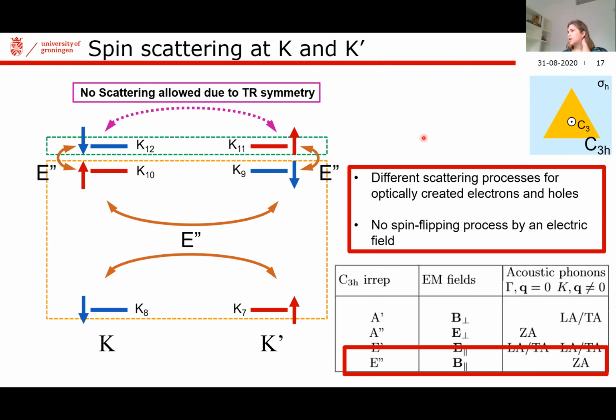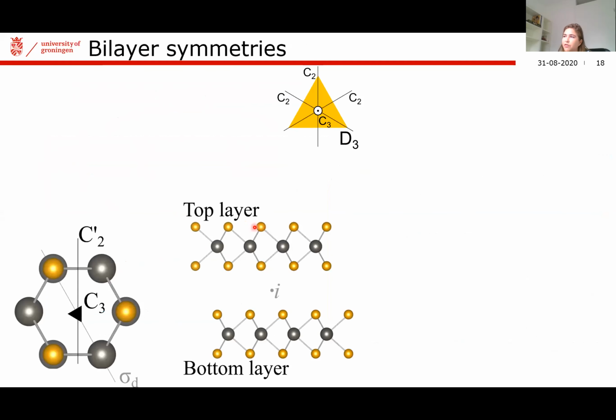So for this first part, what I need you to take home is that the symmetry of the wave functions in the conduction band and in the valence band are very different. And that actually leads to different scattering processes for electrons and for holes. Also, if you look at this table and you look at the electric fields, there's no spin flipping process that is provided by an electric field for a monolayer TMD. Right? So they should be quite robust with respect to the presence of local electric fields.